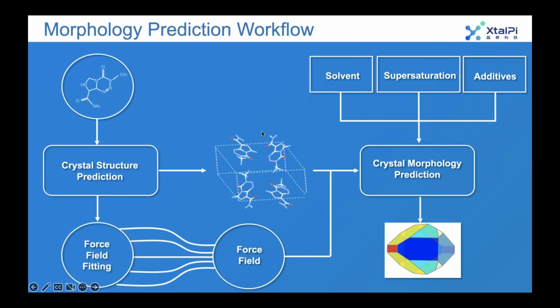Yeah, so since the input is the crystal structure, right, what we could potentially do is do predictions on two different polymorphs, right? And then we could look at the interactions between the solvents and those particular polymorphs and the morphologies that were predicted. What we could also do is potentially a templated nucleation and growth project there, right, where we could look at how different templates interact with those polymorphs. But by design, these simulations shouldn't show us a polymorph transition. That shouldn't happen. They're not designed for that.